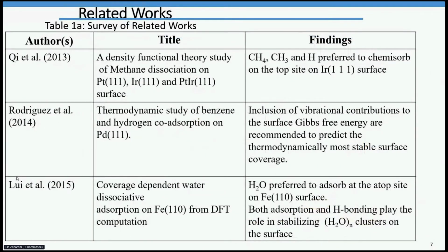Yet our 2013 work, titled Density Functional Theory Study of Methane Dissociation on Platinum, Iridium and Platinum-Iridium Surface, found CH4, CH3 and hydrogen preferred adsorption on the atop site on the iridium 111 surface. Rodriguez et al. 2014 did work titled Thermodynamic Study of Benzene and Hydrogen Co-adsorption on palladium 111 surface. The inclusion of vibrational contribution to the surface Gibbs free energy is recommended to predict the thermodynamically most stable surface coverage.